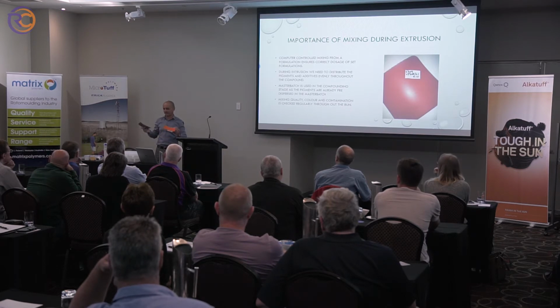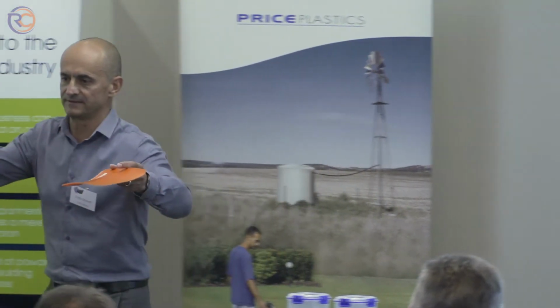I'll pass these around, but this is actually a melt out of powder. We also do a press out straight after the compounding line when we first start, and this is a sample from Price Plastics. But once the machine is started, we actually check the powder, and we do a melt out of the powder, because it also highlights other issues like orange peel, and it shows up dispersion and incorrect mixing a lot more accurately. So I'll pass these two around.